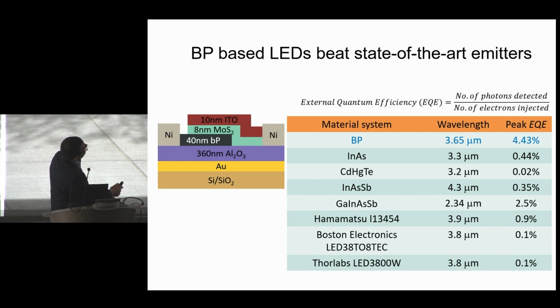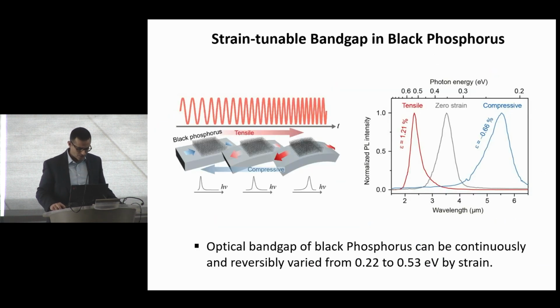today. So here is a table of what you can buy today, compared to black phosphorus. This is for an LED, looking at the external quantum efficiency. Our BP device is at 4%, and the wavelength that it's emitting at is 3.6 micron. The only number that you see that is bigger, that comes close to it, is for gallium indium arsenide antimonide, but it's for a much shorter wavelength. It's for 2.3 micron. So you can see that we are already better than what the state-of-the-art can do.